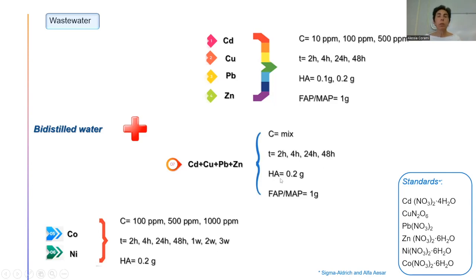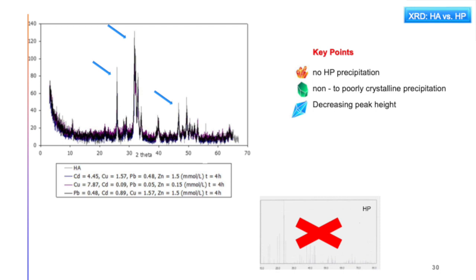And then we only used one amount for the hydroxyapatite and 1 gram for the fluorapatite from US and Morocco. And then we studied the same phosphate for cobalt and nickel, but we increased the concentration from 100 ppm to 1000 ppm, and we increased the time from 2 hours to 3 weeks, but only using as an amendment the hydroxyapatite with an amount of 0.2 grams.